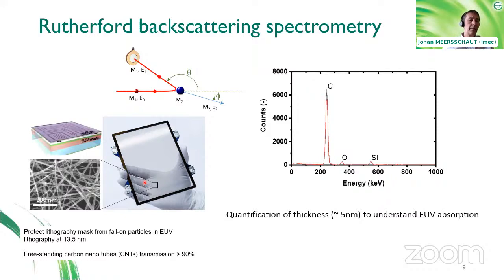But on the other hand, there's also a very harsh environment in EUV lithography tools. For example, there is a lot of ionization, and the radicals inside that tool are attacking the nanofiber which is posed here. So there is a lot of research going on in characterizing these materials. And on the right here, you see an actual RBS experiment on such a pellicle. You see that we are very sensitive to the carbon, even if this layer has an effective thickness or an equivalent thickness of the order of 5 nanometer.